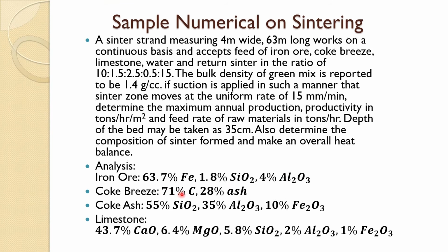63.7% iron, 1.8% silica and 4% alumina. Coke breeze about 71% carbon, 28% ash, and the ash analysis is 55% silica, 35% Al2O3, 10% Fe2O3, and limestone 43.7% lime, 6.4% magnesium oxide, 5.8% silica, 2% alumina and 1% Fe2O3.